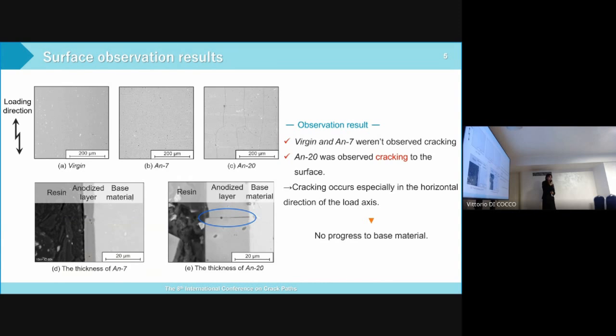This is the surface observation result. A to C shows the result of surface observation on each specimen. As a result, cracking was not observed on the virgin and AN7, but cracking was observed on the surface of AN20. Cracks were observed to occur randomly, especially in the horizontal direction of the load axis. When the cracking was observed in the cross section of the anodized film, as shown in D and E, it was found that the cracking did not propagate into the base metal. Moreover, pits were observed in the anodized film, regardless of film thickness.